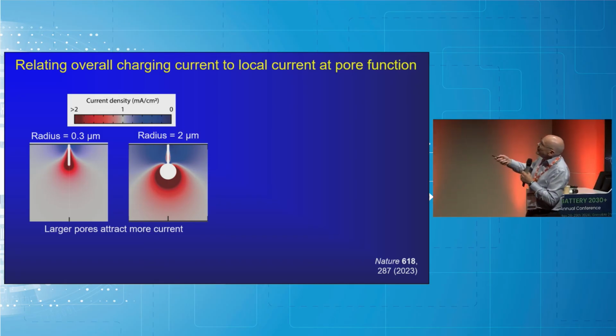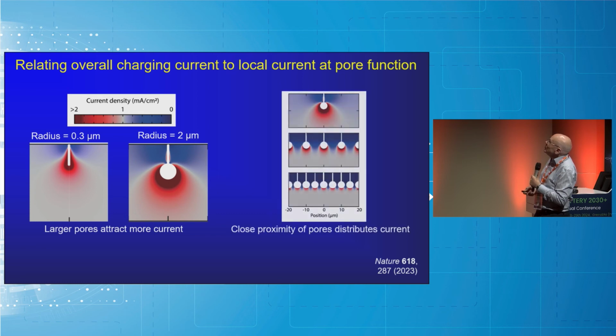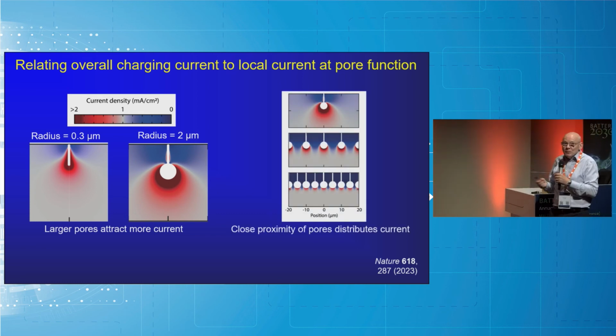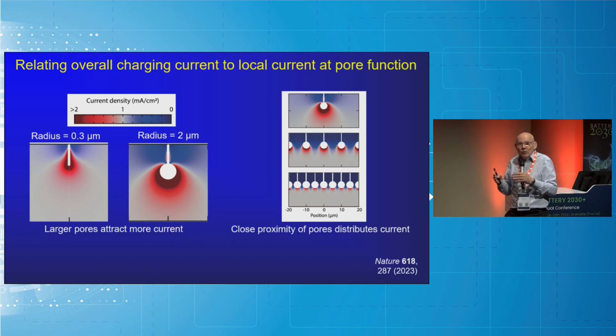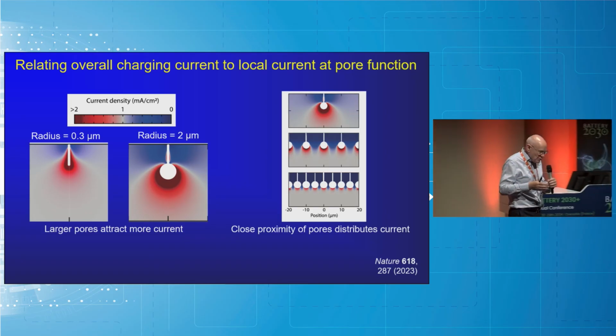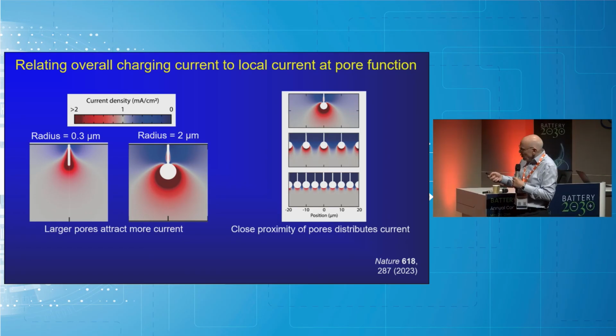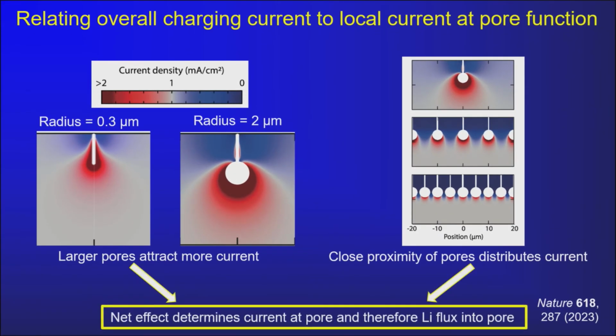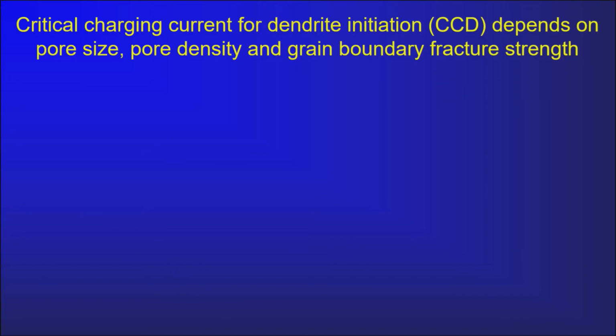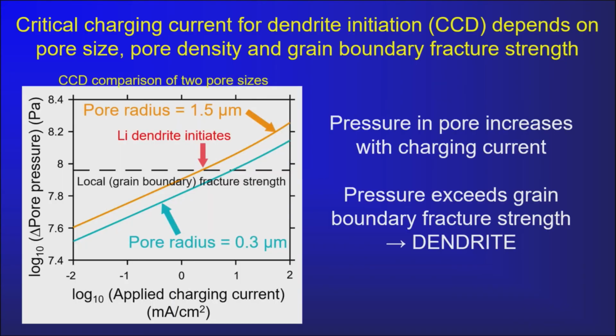The larger the pore, then the more current, so that's going to make it worse. We also have to take account of the fact that there's a distribution. There's not just one pore, but many pores. And that distributes the current density. So we have to take all of these factors into account in working out the relationship between the current and the pore pressure. And that's what we've done here.